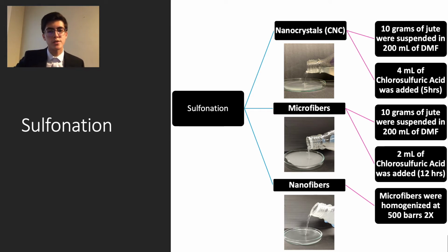In parallel to this reaction, the microfiber reaction was run, where 10 grams of jute was suspended in 200 milliliters of the same organic solvent, and 2 milliliters of chlorosulfuric acid was added and allowed to run for 12 hours. Following the microfiber synthesis, a portion of the product from the microfiber reaction was homogenized at 500 bars 2 times to yield nanofibers.